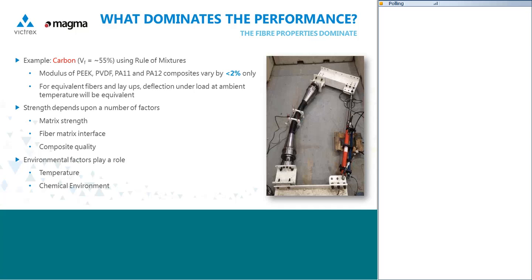Although the fibers are dominating the performance, elevating the temperature and making the chemical environment more aggressive, all of these things will attack the matrix material, and as that degrades, then obviously the properties of the composite will decrease. So if you have a significantly more chemically and thermally resistant matrix, you will have a significantly better performing composite. Although all of these materials appear to have very similar properties at the outset, once you start talking about environments and temperatures, you see quite a different picture.